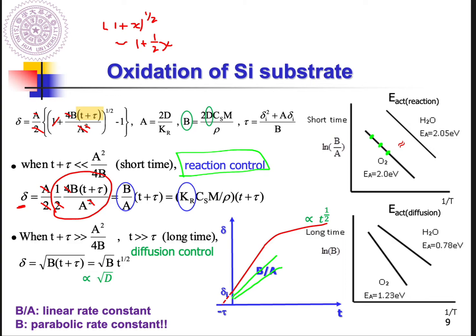that becomes diffusion control. So you can also do the same thing. You can measure the thickness of the oxide layer for a longer time, and you get the slope here. You take the log B versus 1/T, and as you know, what's inside the parameter B is embedded the activation energy, exponential of minus activation energy over kT, right? This is exponential. So you take the log of this value versus 1/T, then the slope will be minus activation energy divided by k.